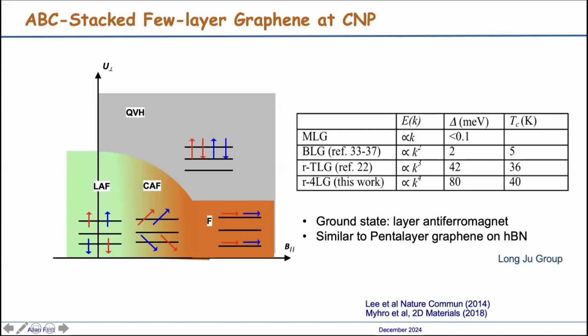Okay, so that just shows that there are a lot of interesting phases possible in this system. It just depends on whether you screen or not. When we suspend the sample, we minimize screening, so the Coulomb interaction is largest. So at the charge neutrality point, we get the layer antiferromagnetic state. When you put devices on hBN, this state is only observed in 5 layers because you have more screening, but the band also becomes flatter in a thicker sample.